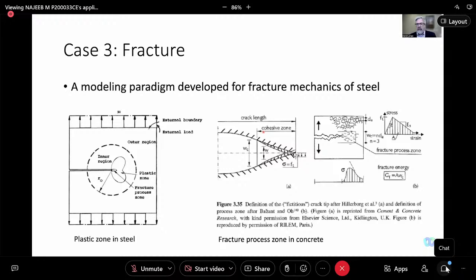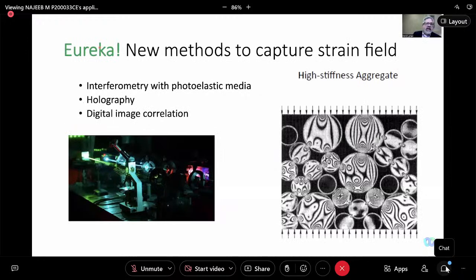And some of them needed to be investigated in a careful way because it meant that you had a field of strain or a stress distribution that was complex around the tip of a crack. How are you going to measure that? Well, the new eureka here is new methods to capture the strain field. And we've seen some very interesting things done with interferometry and photoelastic materials to capture the state of stress or the state of strain. This is really the strain distributions. And in ACBM, in those early days in the 90s, we had holographic experiments and digital image correlation as ways of getting this kind of result from a physical test.